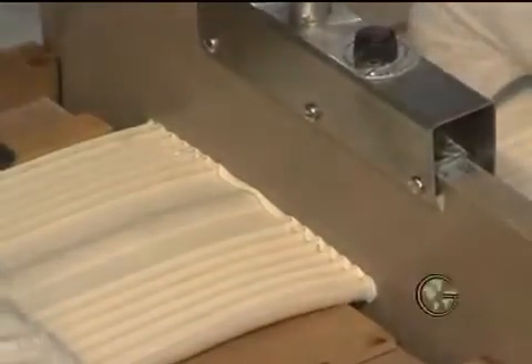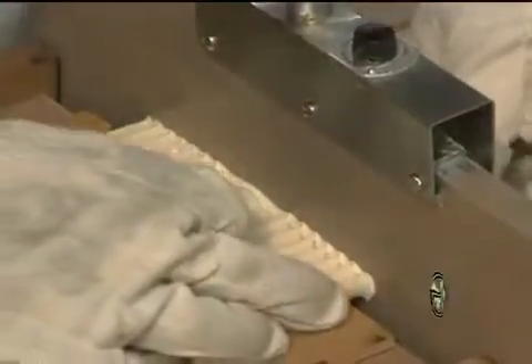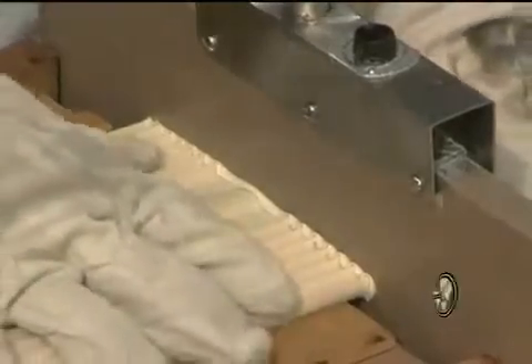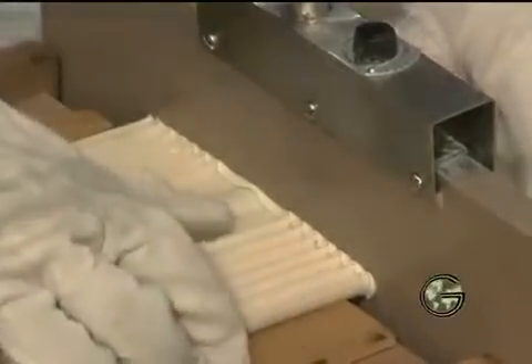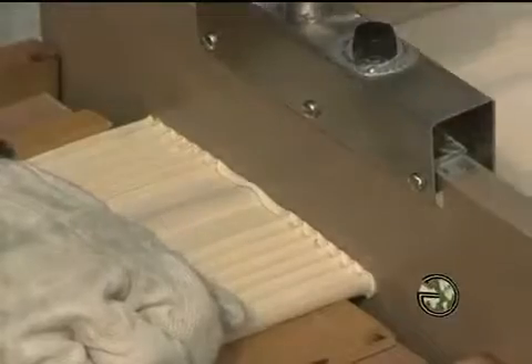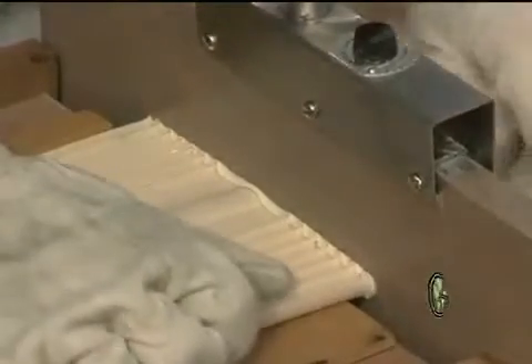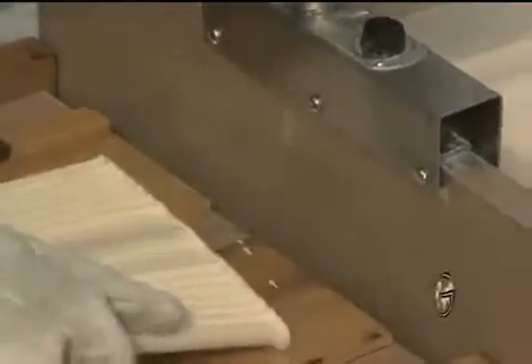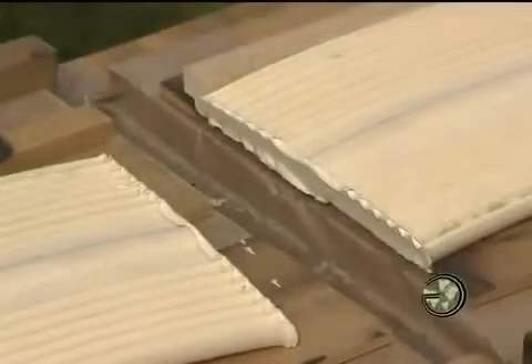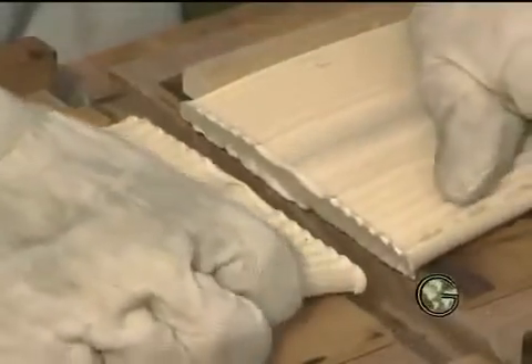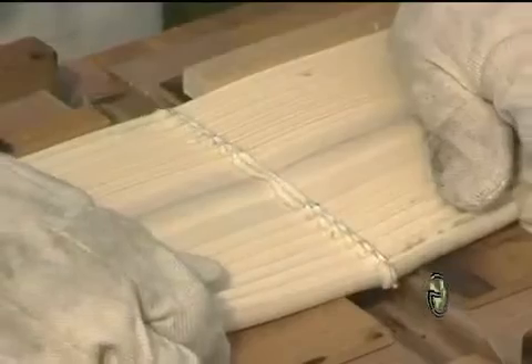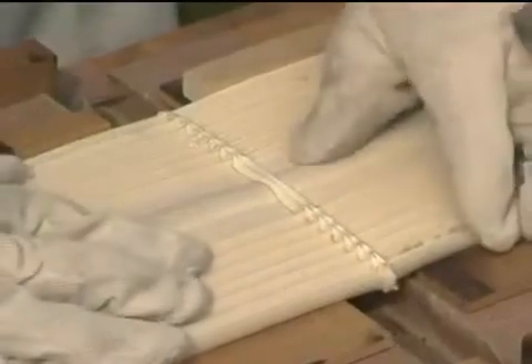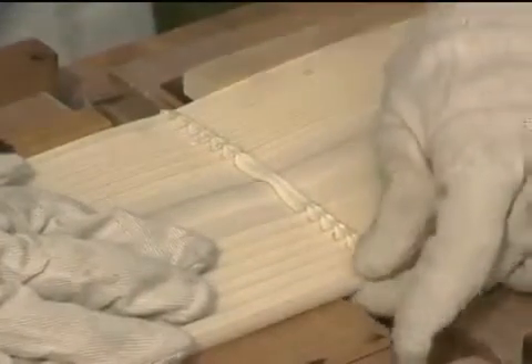In order to achieve an adequate bead, it is important to apply sufficient and uniform pressure between the entire water stop cross-section and the surface of the iron. This will also prevent unmelted spots along the face of the water stop. Once sufficient melt is achieved, remove the adjoining ends simultaneously from the iron with a quick jerking motion, which ensures that the melted PVC remains on the end of the water stops and not on the face of the iron.